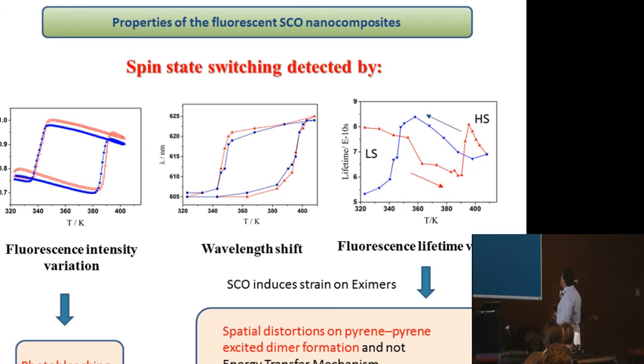But we know the distance, because we have the spin crossover nanoparticles, the shell of silica, and then the fluorophore. So the distance between the fluorophore and the spin crossover is quite high. So we think that this fluorescence modulation is better explained by the spin crossover induced strain on the excimer. During spin crossover, you have volume change in these materials. This volume change induces distortion in the dimers, so you modify the interaction between the dimers. That's why you have these modulations.